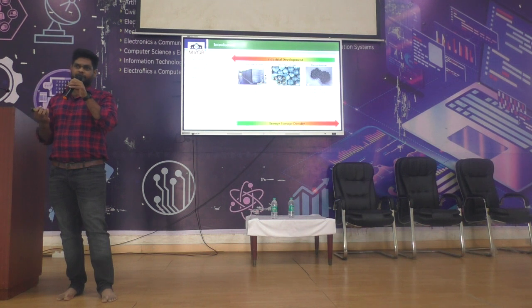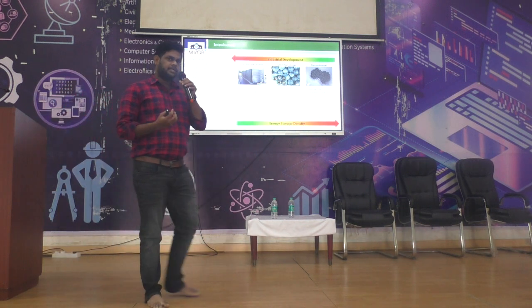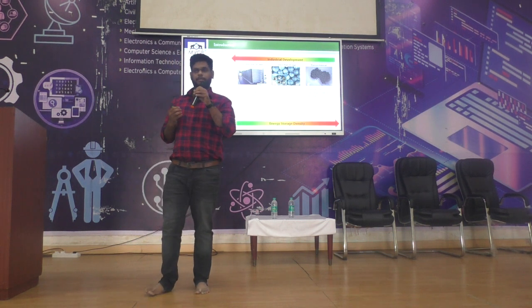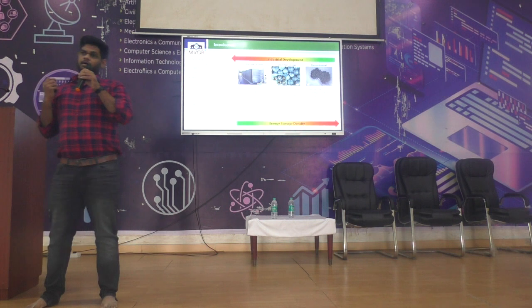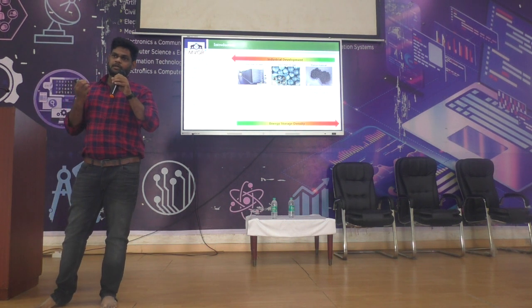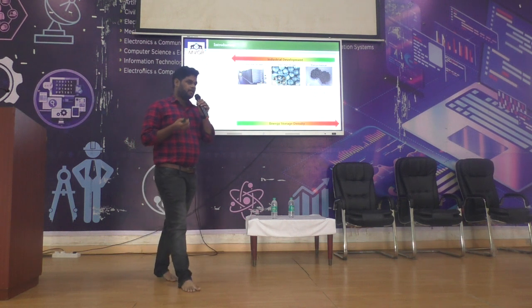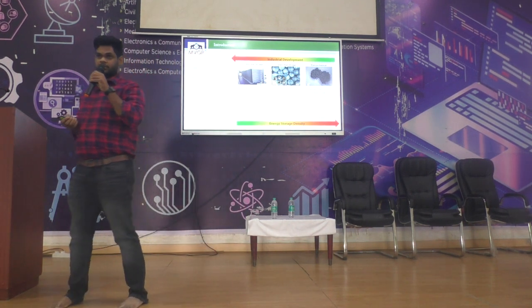The mass is 10 kg, it has some specific heat capacity, and we heat it from 30 degrees to 90 degrees. Let us assume that. So what is the sensible heat storage? It will be m Cp delta T. We all know that. Here the heat is stored in the form of sensible heat, so it is directly proportional to the mass of the material, and also directly proportional to the specific heat capacity and the temperature difference.